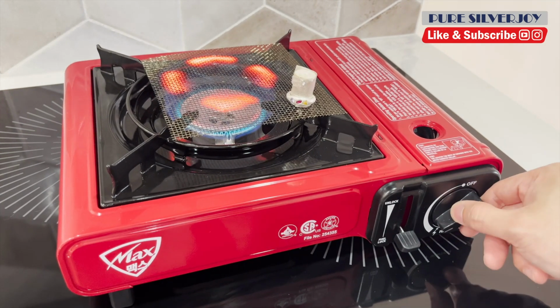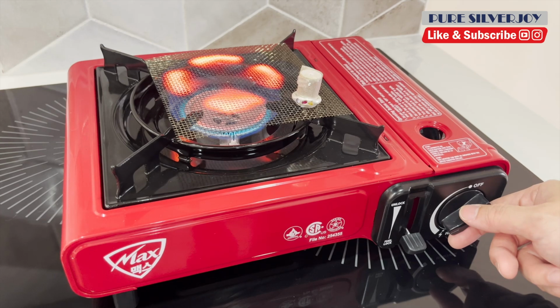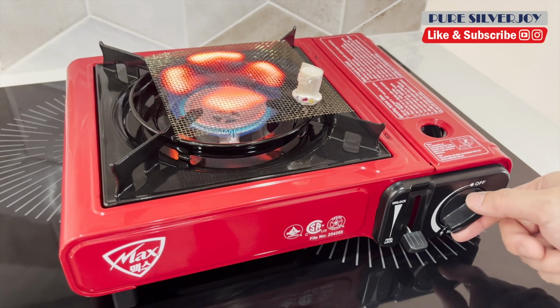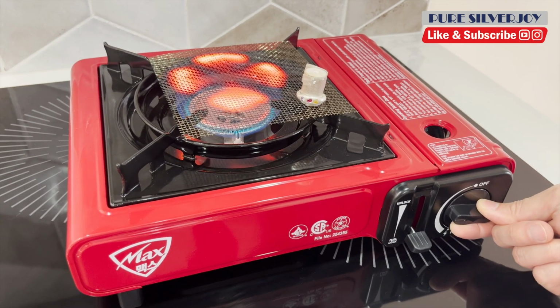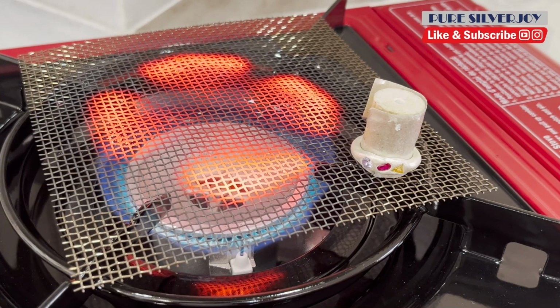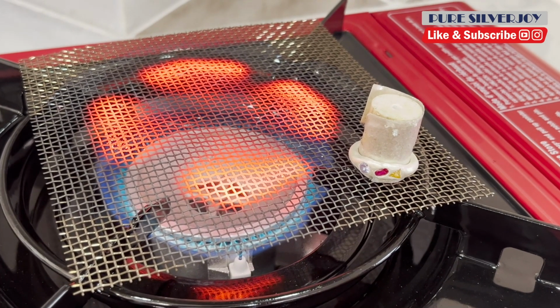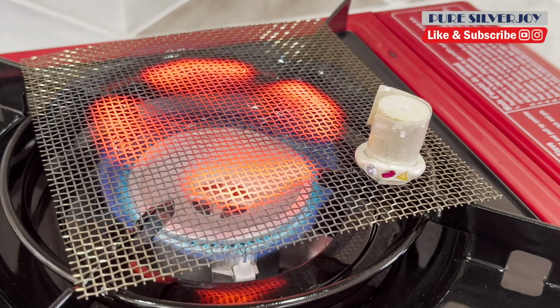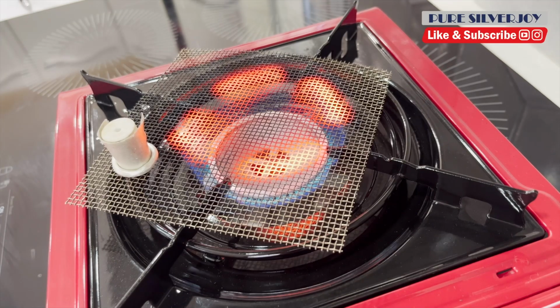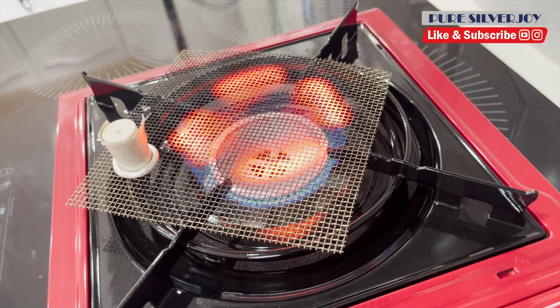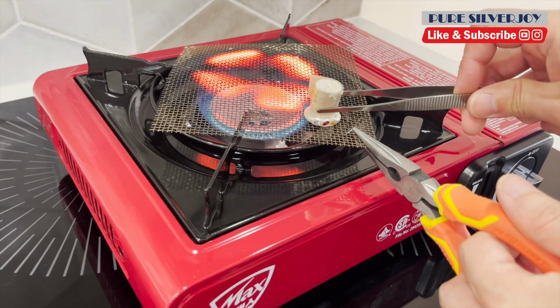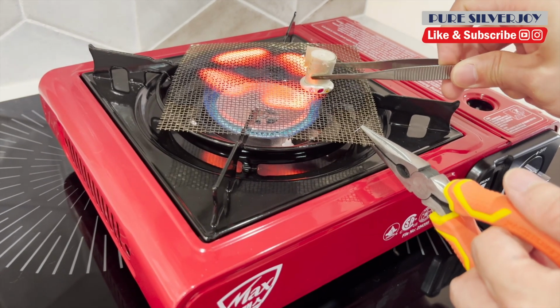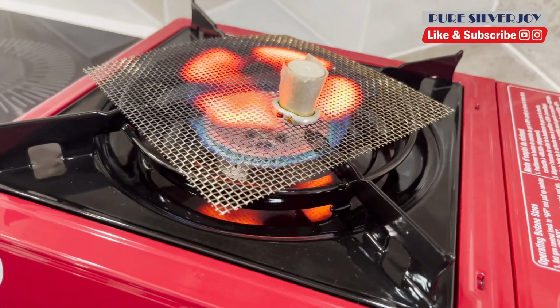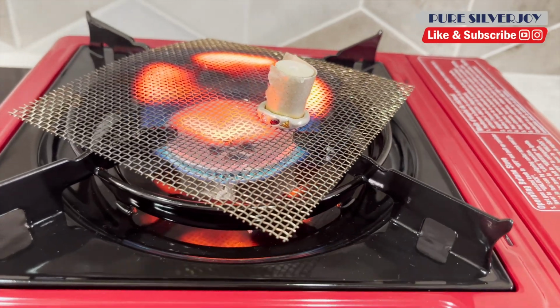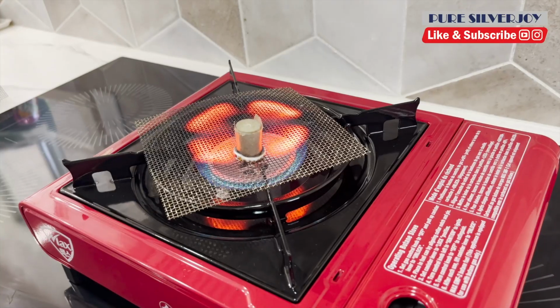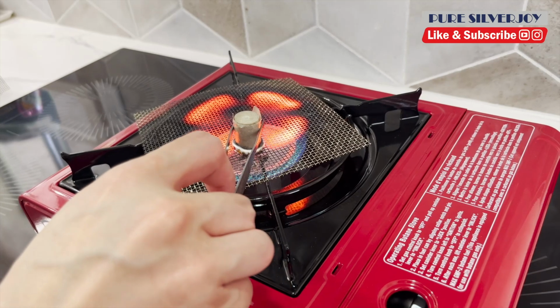If using a kiln, set the temperature to about 800 degrees Celsius, 1472 degrees Fahrenheit, and fire for 10 to 15 minutes. If using a gas stove, start by heating the ring at the edge of the flame with low heat for 5 minutes to warm it evenly. Then move it to the center of the flame, gradually increasing to medium for 5 minutes. And then high heat for around 15 to 20 minutes.